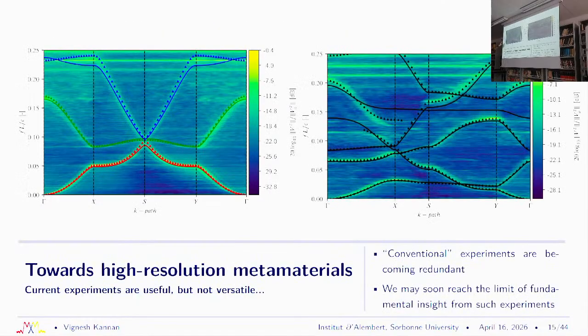Right, so what I'm showing you here is the square unit cells, and here I'm showing you data from the rectangular unit cells, and you can see of course that the dispersion relations are much more complicated here because we broke one of the axes of symmetry. And if you go to much higher modes right here, you'll actually begin to see that there is deviation of the lines from the experimental data, right? So it works with limitations.